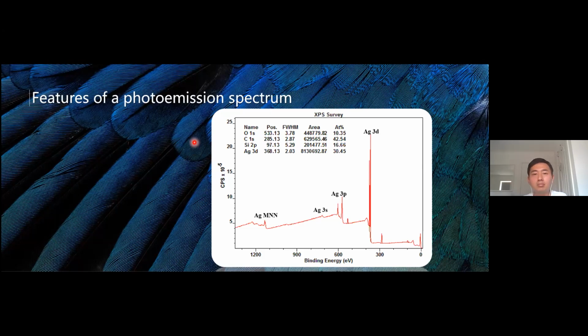So a typical feature of a photoemission spectrum - this is a wide scan of an XPS spectrum. We could see that there are peaks originating from the oxygen 1s orbital at 533 binding energy, and carbon below 300.